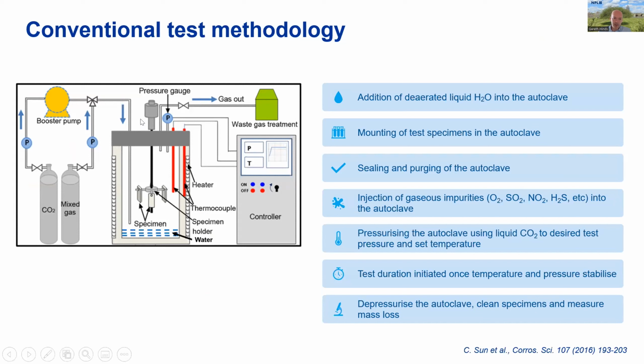It's an autoclave, in other words, a pressurized vessel where you can pump in CO2 and different impurities to control the environment that the specimens are exposed to. These are metal specimens, coupons of the pipeline material, usually cut from a tubular pipeline itself, so that the metallurgy of the specimens matches that you see in the real pipeline in service. Then some liquid water is placed at the bottom of the autoclave. Its mass has to be carefully controlled so that the composition matches, again, the worst case scenario typically that you're envisaging during service. And then the specimens are typically mounted into the autoclave.